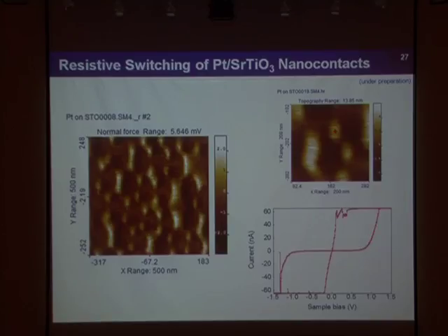Actually, this experiment was done in an ultra-high vacuum environment, at a 10 to minus 10 torr vacuum level, so we cannot expect any environment effects at all. Even so, in such cases we still get clear switching behaviors, so I should say this switching is mainly due to electron trapping effects.